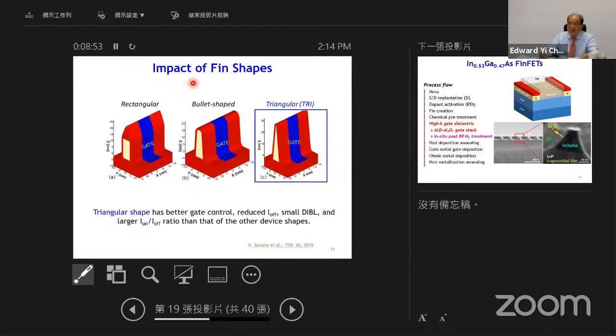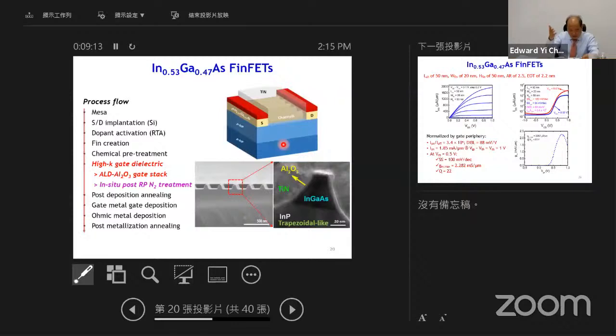Next one. To maximize performance, we can use different configurations of the fin shape, and here using the triangle, we get the best performance. So the next one is to make the indium gallium arsenide FinFET, because we use this configuration and we use high-K dielectrics, including aluminum oxide or hafnium oxide, and then we use plasma treatment.